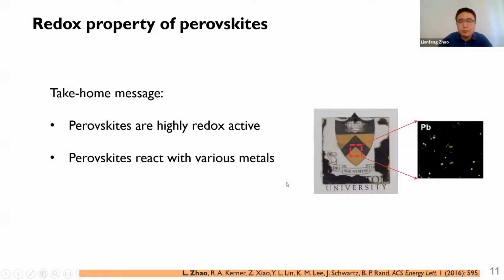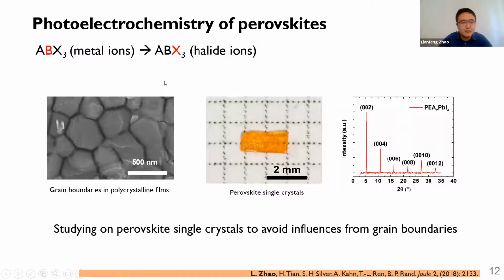So the take-home message for this part is that perovskite is highly redox active, and it can react with many different metals. And also, the reason the sample becomes transparent is that the metallic lead aggregated so that it only scatters the light rather than blocking the light. That's why the full device stack becomes fully transparent. So I just showed you how the metal ions contribute to the chemical properties of perovskite. In the next part, I will show you how the halide ions contribute to the instability.